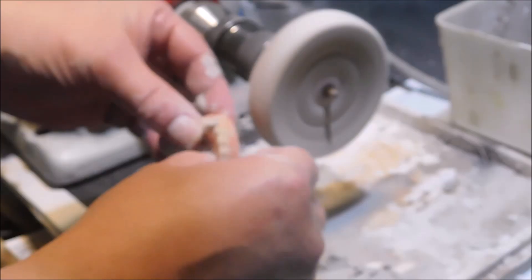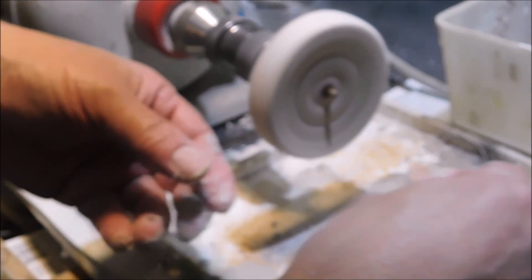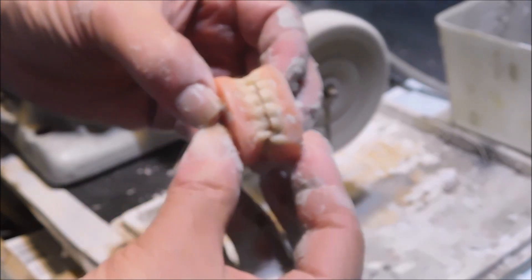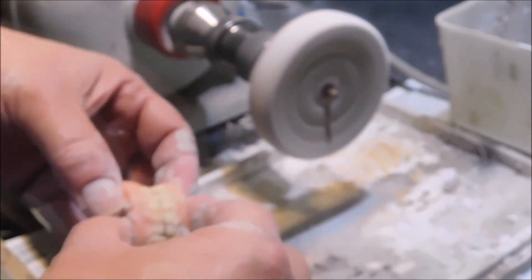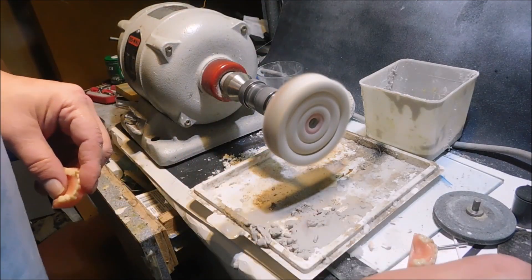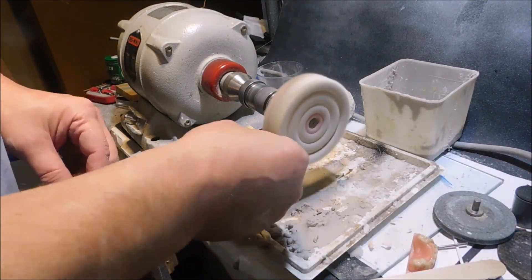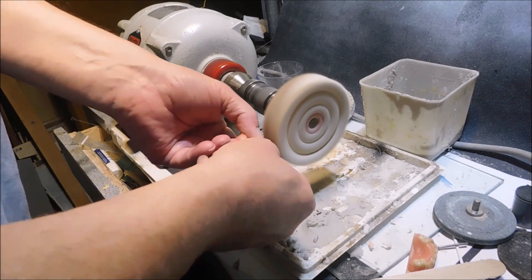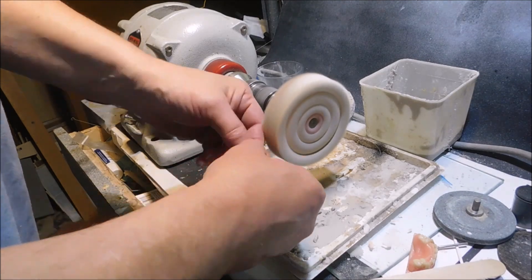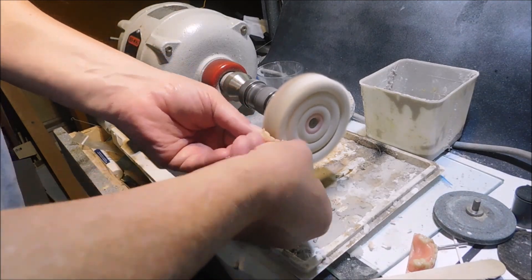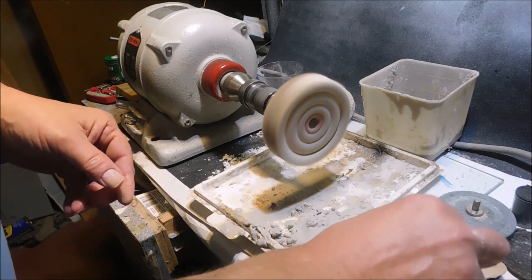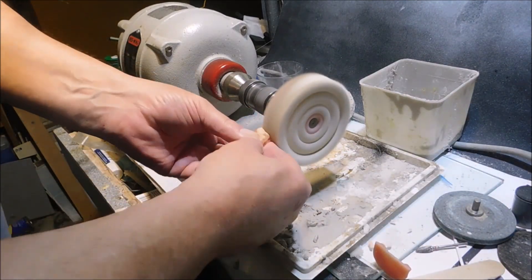Back to these teeth - I'm pumicing with wet pumice. This is a rag wheel - you have a pumice wheel and a polish wheel - and you have this polishing compound called rouge. You simply polish these teeth. My rag wheel is a little damp because you can burn the acrylic. You'll have these shining just like dentures. It did well, I'm happy with it.